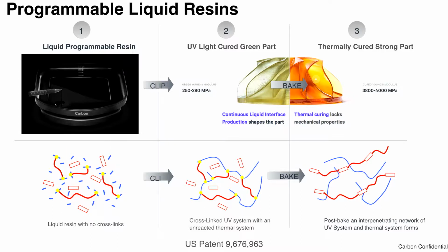And so we developed a process that we call programmable liquid resins. Essentially, we use light to lock shape, and we use a secondary chemistry through a thermal process to actually provide its mechanical properties and create those chain entanglements. And so you see vastly different mechanical properties after print and post-bake. An example is the cyanate ester material.